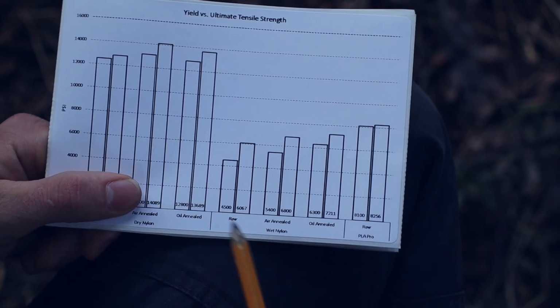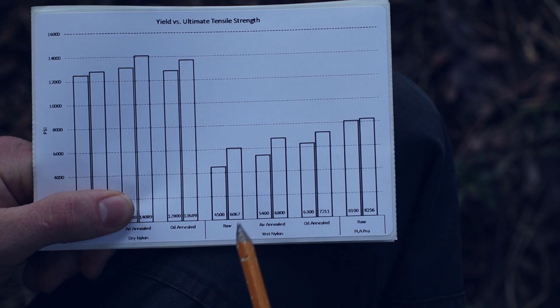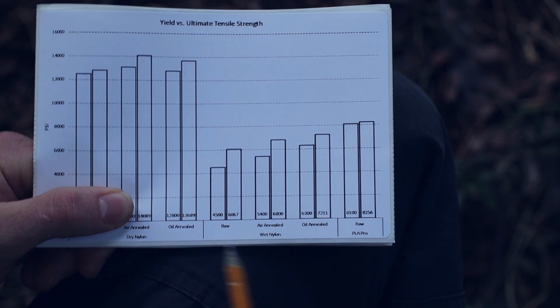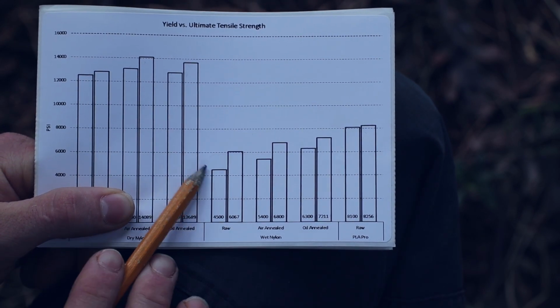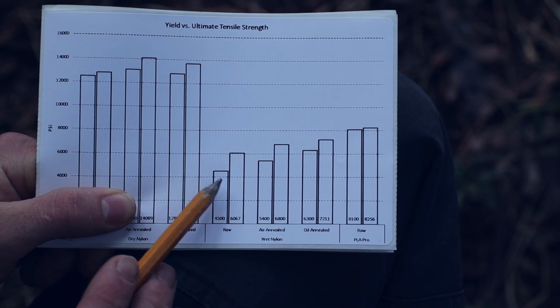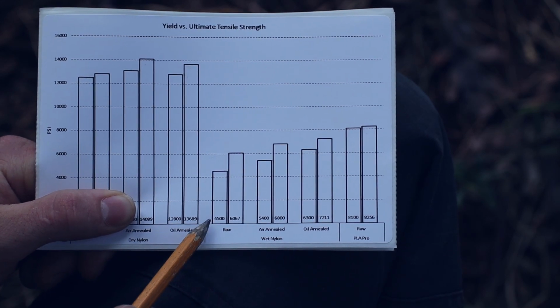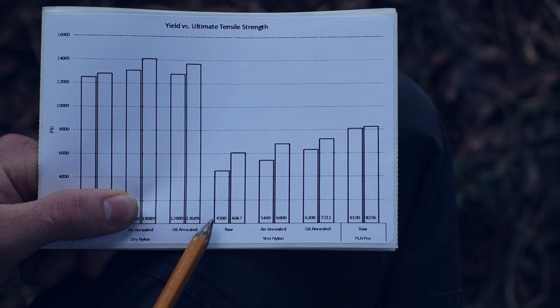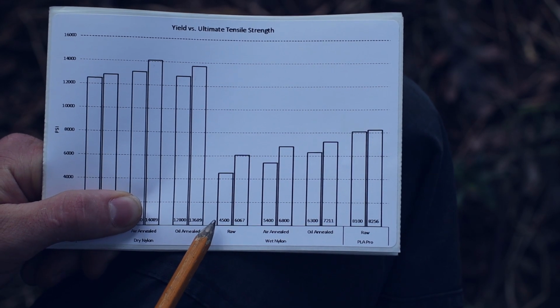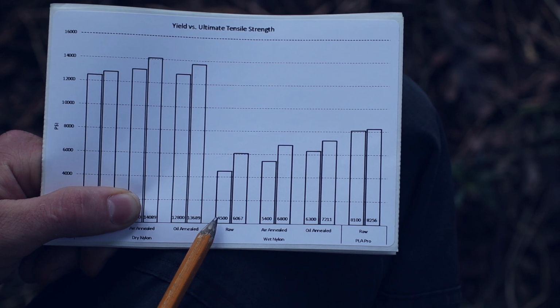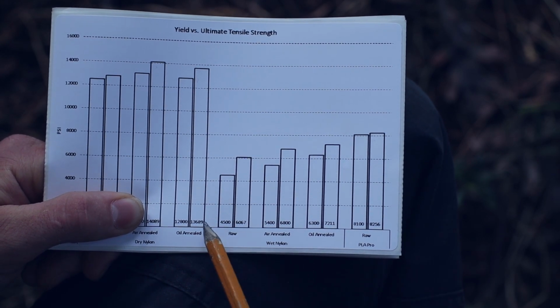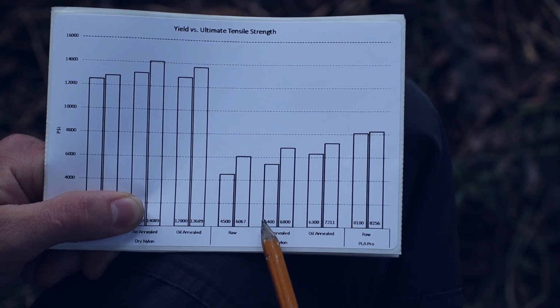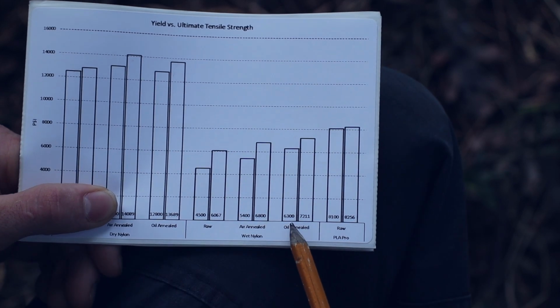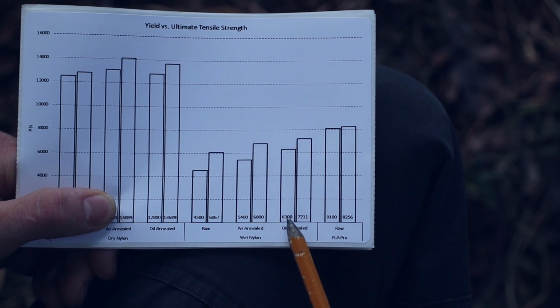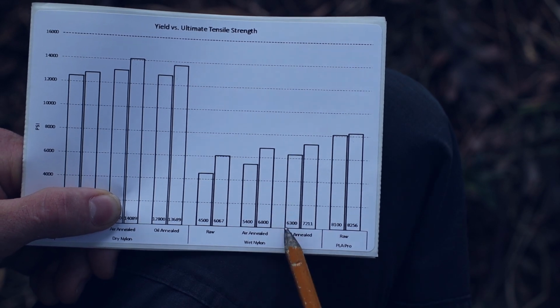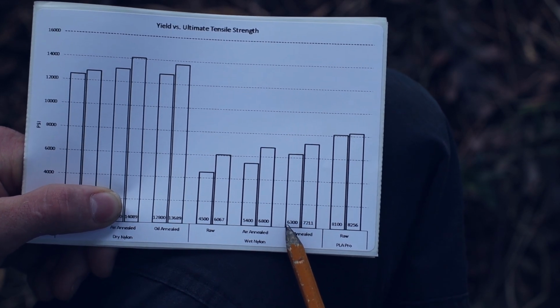So that's kind of interesting that after annealing, they actually became slightly more ductile, and there was more plastic deformation before failure. What really starts getting bad is when we jump down here and look at our wet values compared to the PLA Pro. So down here, after moisture absorption, there is a lot of plastic deformation. Our yield strength on the raw unannealed nylon drops down to 4,500 psi, which is ridiculously low, not strong. At 4,500 psi, we're now beginning to get failures. That's really bad. Looking at air annealed, that jumps up to 5,400, which is a significant increase, but still pretty bad. Oil annealed is significantly better, and we're up at 6,300 psi for the yield point, which, while still being really bad, is way better.